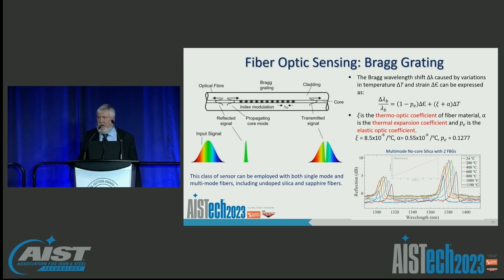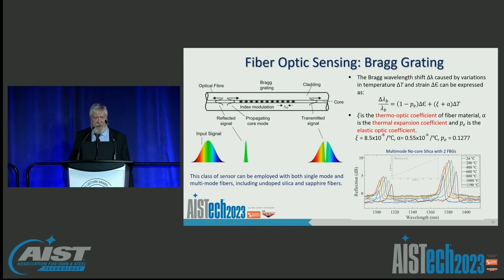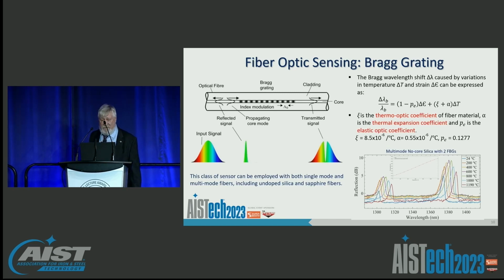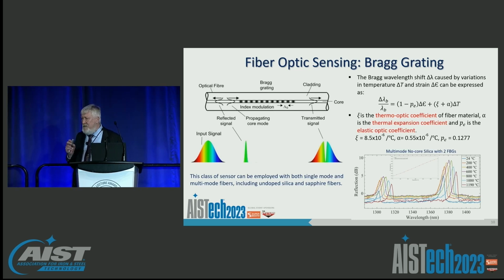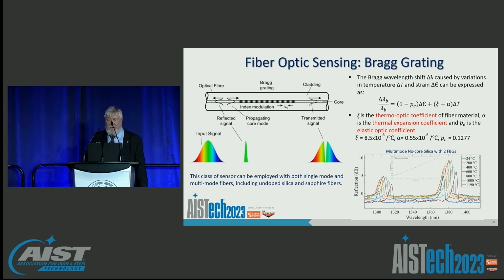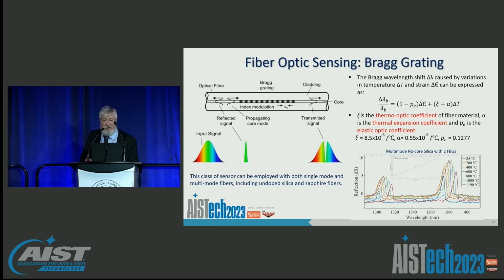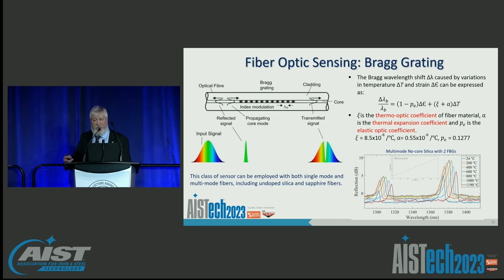The most common method you'll see out there, and many of you have seen these in continuous casting molds, is the fiber optic sensing system using Bragg gratings. Bragg gratings are generated with a fixed spacing between those etched Bragg patterns such that the reflected frequency is a function of the spacing of those Bragg gratings. And so each grating is etched into a fiber as a sensor. It can be etched with a certain spacing that gives you a base frequency. But frequency shifts as a direct result of temperature or strain due to something called the thermo-optic coefficient or the thermal strain coefficient. And as a result, this type of technology is very well suited for measuring temperature shifts and strain, in some cases to very high temperatures. And I'll show you some examples where these types of fibers of the right type can actually measure temperatures up to 1800 centigrade.